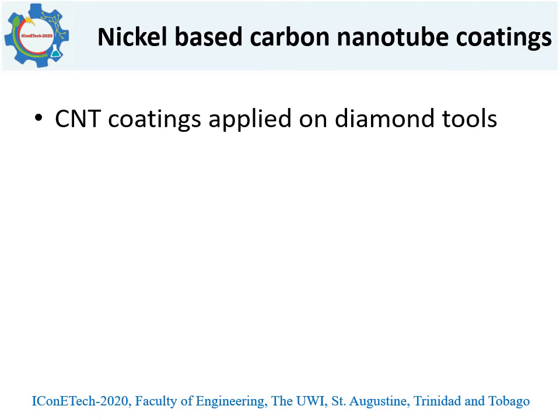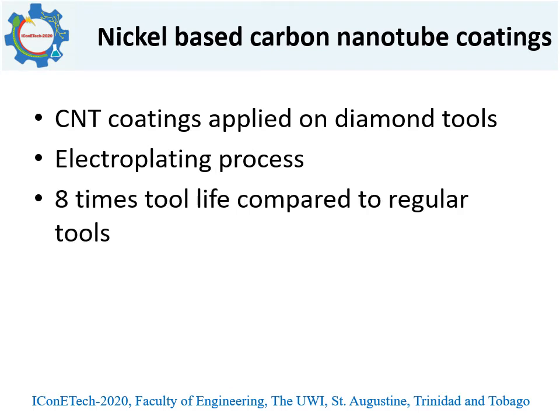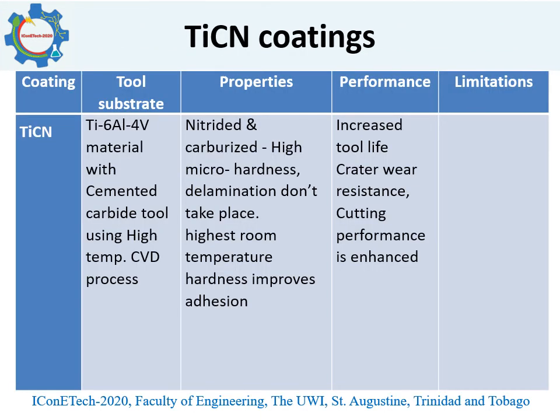Now, carbon nanotube coatings: because carbon nanotubes have extremely high strength, normally these are applied on diamond tools using an electroplating process, and it has been noticed that the tool life of the CNT coated diamond tools is 8 times that of uncoated tools. Some of the applications, like titanium carbonitride: the substrate is a titanium material with cemented carbide tool using a high temperature CVD process. Nitrided and carbidized, it has high micro hardness, delamination does not take place, and the highest room temperature hardness improves adhesion. Performance-wise, it increases tool life and crater wear resistance.